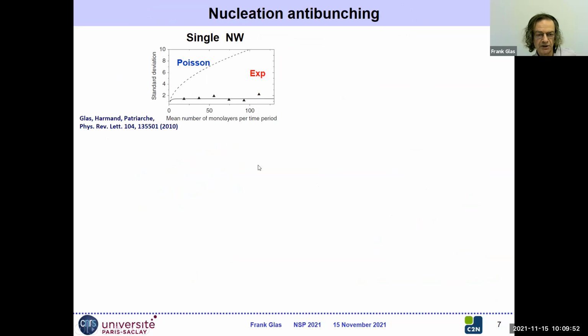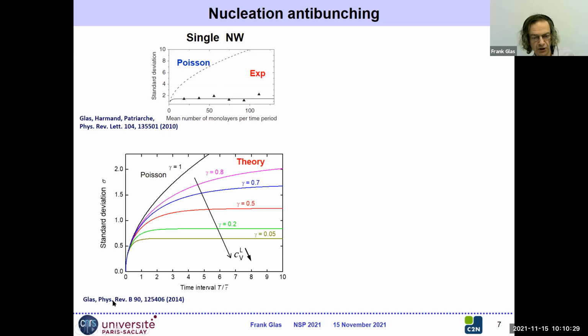That has interesting consequences because nucleation is still random. So the number of monolayers that we get in successive equal intervals fluctuates. So there is an average, but there's also a standard deviation. If the process was Poissonian, you all know that the standard deviation would increase as the square root of the average number of events in these sequences. But what we observed and what we could calculate was in fact something which saturates very quickly at a value which is much lower than the Poisson value. And this could be reproduced by calculation, numerical and analytical. Here is an analytical calculation.